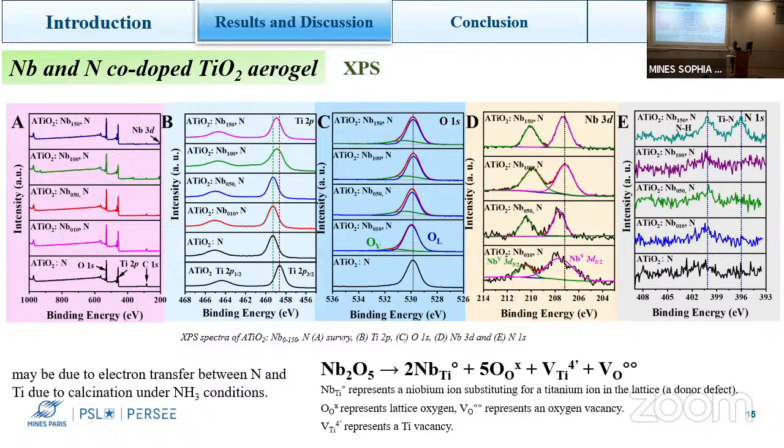Compared with no nitrogen doping, the only change is the nitrogen. So here I think it's due to electron transfer from nitrogen to titanium, and maybe also from the ammonia reducing effect, which generates titanium-3. Also could be, but in our case, I cannot separate the titanium-3 in my spectra. So maybe that is showing up as the shift, but not as a new species.